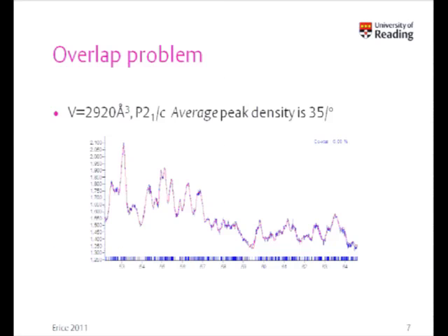This is, I should emphasize, on a lab data set collected at 1.5, so this is a roughly 1.5 angstrom resolution. We'll see that we're up to a peak density of 35 reflections per degree. Now, you'd be lucky if you could identify 35 intensities, full stop, in that region. So that gives you some idea of the amount of bunching up that you have seen, again of the type that Lynn illustrated very clearly earlier on.